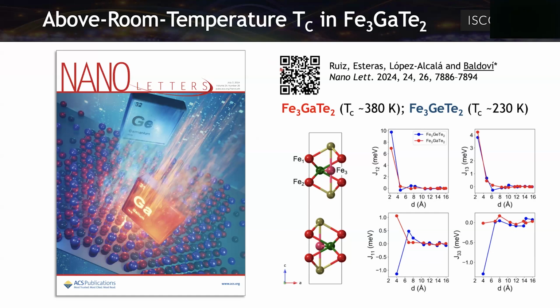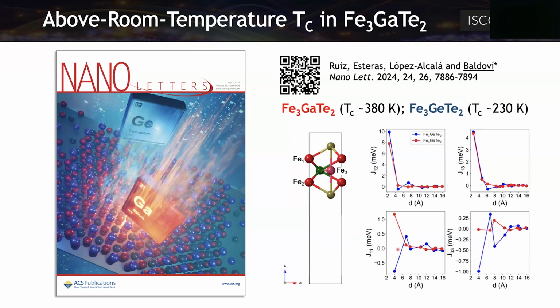Okay, I'm almost finishing. Just introducing this very recent work that we have published. We are comparing the properties of iron gallium telluride with iron germanium telluride. They have similar chemical structure, just replacing germanium by gallium, and there's a big enhancement of the Curie temperature. And we observe that when we have interactions that are in the same plane, in the case of germanium, this is antiferromagnetic, and we should switch to a ferromagnetic one here. And this is in the bulk, but when we go to the monolayer, we have the same effect.